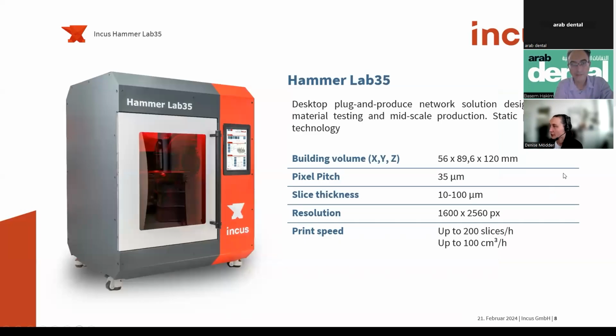This first machine here is a Hammer Lab 35. It's our plug and produce solution. It's really easy to install, really easy to use. It has a build area of 56 times 90 millimeters and can go up to 120 millimeters in height. It has a pixel size of 35 micron that will contour and design the parts. And we can have different layer thicknesses from 10 to 100 micron, while we normally use for stainless steels more around 25 or 30 micron to really have the resolution and the surface quality for the small parts.